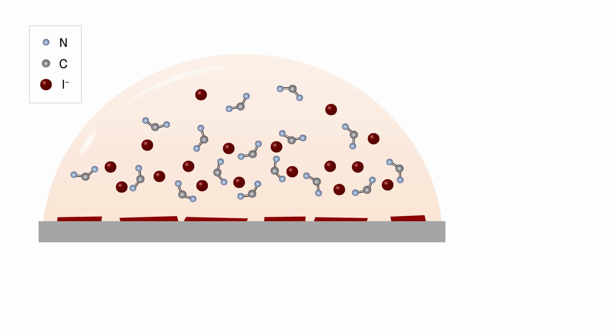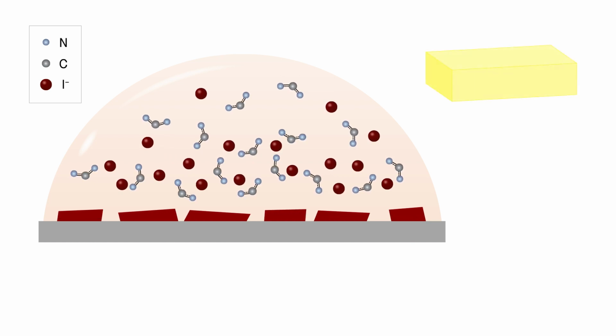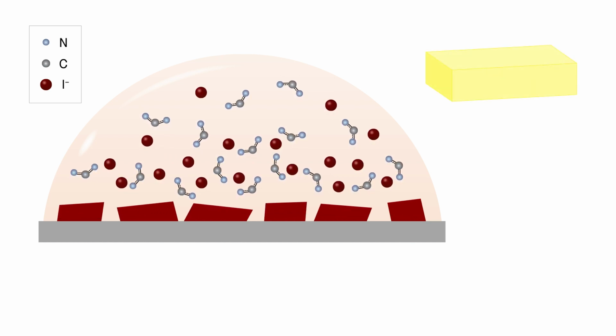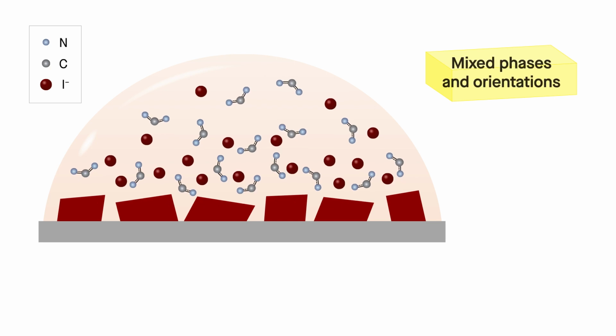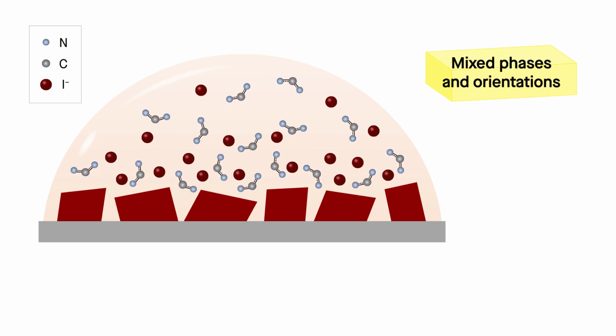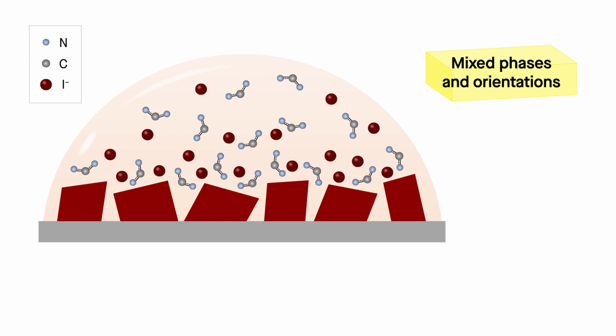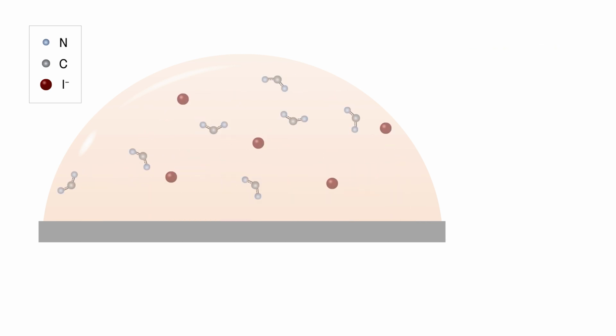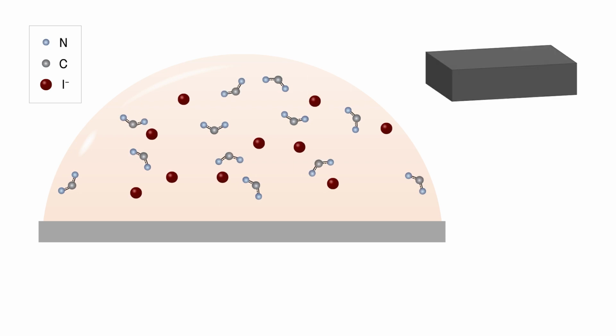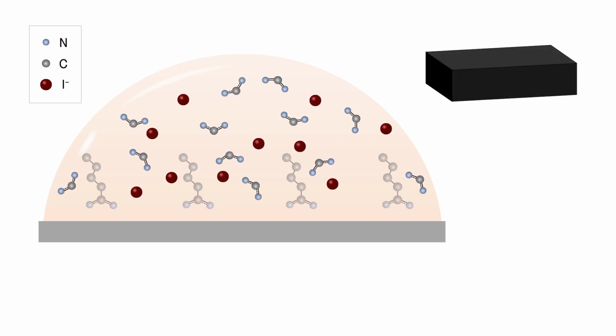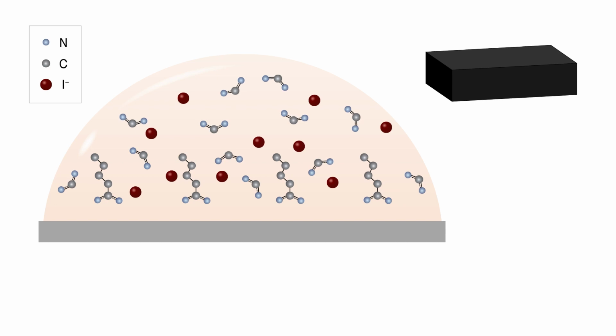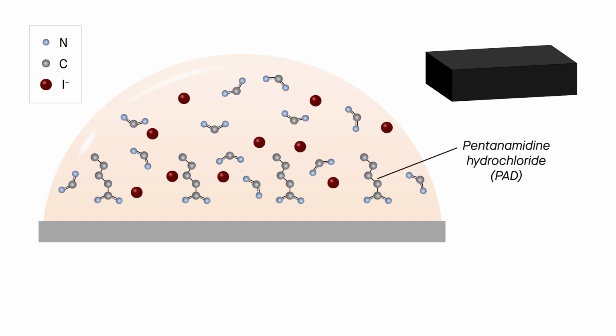What they discovered was that in films with yellow phases, the perovskite grew as a tangled forest of several competing phases, which were oriented at different angles relative to the underlying surface. To clear this forest and make way for the growth of the black phase alone, the team added another ingredient into the mix, the molecule pentanamidine hydrochloride, or PAD.